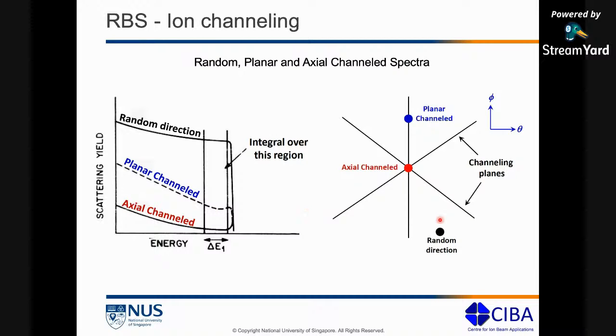But that doesn't mean that planar channeling is not useful. Actually, it is useful in a way that if we want to find the axis, what we typically do is from the random direction, we will first try to find the planar channel. Once we are there, then we just go along the plane until we come right at the axis. So although this is not used in the data that we collect, it helps us to find where the axis is located. For single crystal silicon, it's not that big a problem because the 100 axis or 111 axis is pretty easy to find. But in some of the complex crystal structures, it's not easy to find the actual channel. So what we do is from random orientation, we try to find one of the planes, and then we just travel along that plane until we have a drop in the backscattered yield that tells us that now we are along the axis. Okay, so planar and axial channel spectra form part of ion channeling.